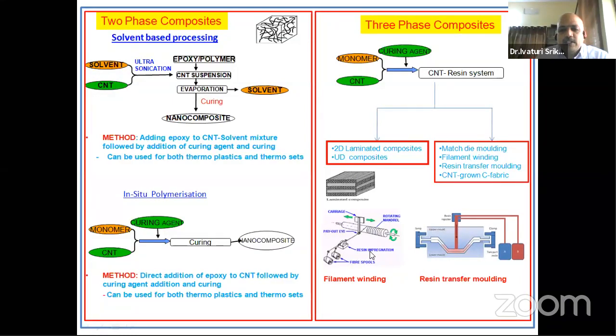But for the actual processes, say for a missile shell structure or an aircraft wing, the technique used is called filament winding. You can see here the carbon fiber spools running through a resin bath. This is resin impregnation. So here you have to mix your CNT added resin system. The carbon fibers should dip into the CNT added resin system and get wetted with that. Then you wind this resin mixed fiber around the shell. After curing, you remove the central mandrel, and you get the shell. So this is called the filament winding process.